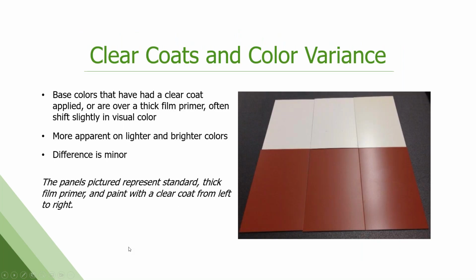Again, we're talking about the color variation. So these clears, like I said, have a very slight yellow tint to them, which means that on a lighter color, like a white or a light tan, once you apply that clear coating, you might see a slight shift in the visual color. You're not going to see it on medium and dark tones. It'll be kind of, can't pick it out of the lineup. But we have some examples here. So the panels on the left are standard primer, standard top coat. Panels in the middle have a high build primer underneath them.